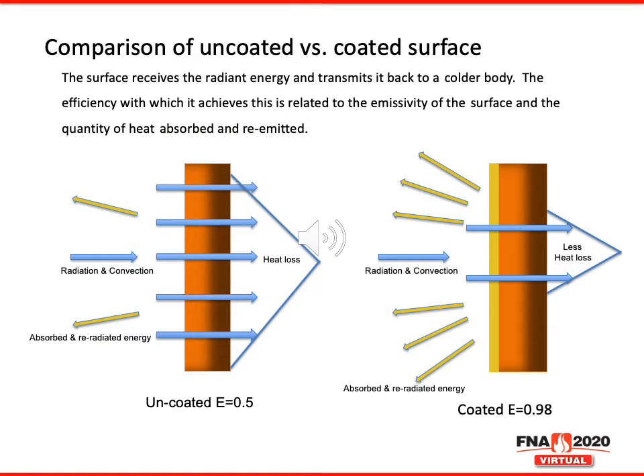The diagram on this slide shows a comparison of an uncoated versus a coated hot face lining in a furnace. This surface receives the radiant energy output by the burners and transmits it back to the colder body or the product that we are trying to heat treat or forge in the furnace. The efficiency with which it achieves this is related to the emissivity of the surface and the quantity of heat absorbed and re-emitted. As you can see, by coating the hot face lining with a ceramic coating, we can greatly reduce the heat loss through the wall.